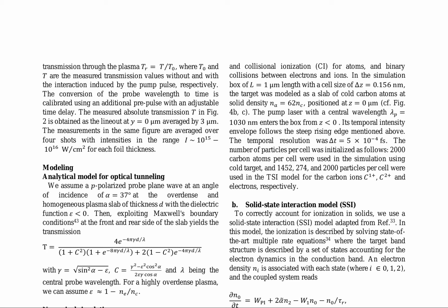To simulate the interaction, two complementary models are used: the particle in cell (PIC) simulation and the solid-state interaction (SSI) model. The PIC simulation, employing the SMILEI code, models the interaction between the laser pulse and the plasma, including multi-photon ionization, field ionization, and collisional ionization.